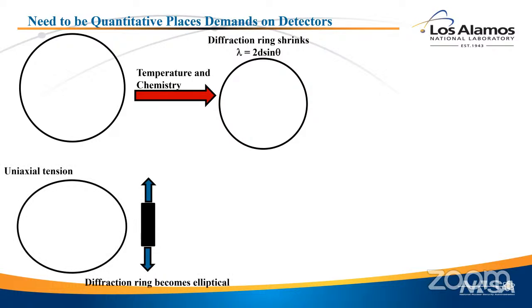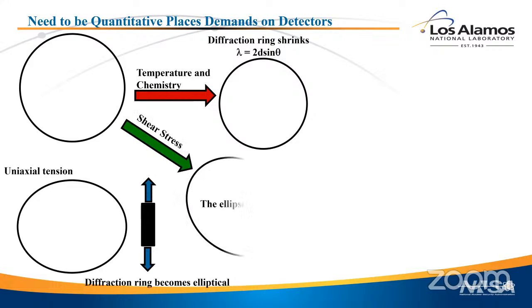Stress, however, gives you a different effect, right? Stress is a tensor. So if I pull on my sample this way, the atoms get further apart this way. That means the Debye-Scherrer cone actually gets smaller in that direction, and it gets larger in the other direction because of the Poisson ratio effect. So that's an effect that I can separate from temperature or chemistry because it's a tensor effect where temperature is a scalar effect, right? So if I measure the full Debye-Scherrer cone or enough of it, I can separate the effect of temperature from the effect of stress. So if I'm annealing something, I can tell the difference between thermal expansion and stress relief, for instance, and you'll see that example, I think.